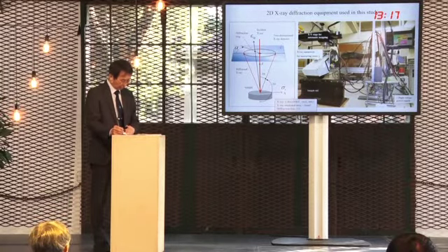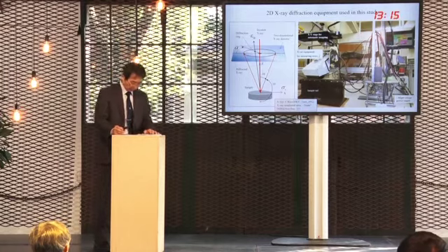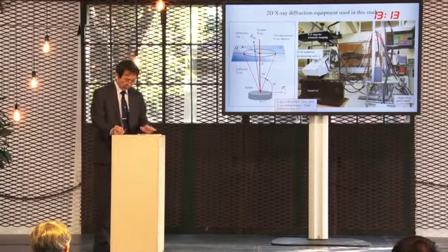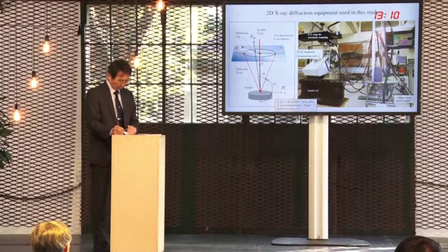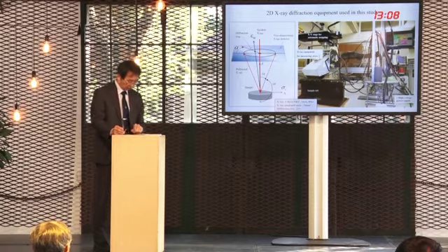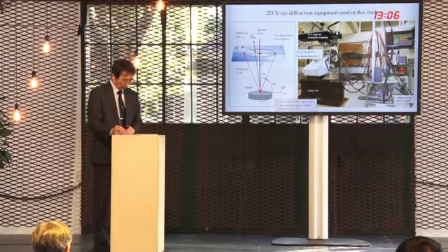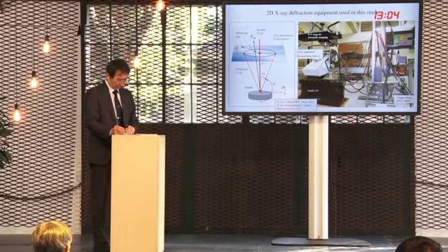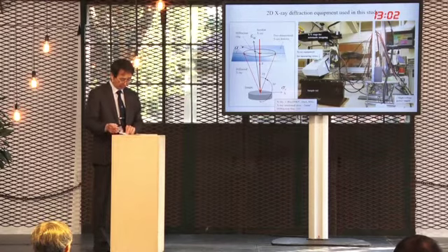The countermeasure to this RCF at the present is ultrasonic testing for detecting cracks and the grinding of rails for removing damaged layer before crack initiation. In my talk, I'd like to show that a newly developed two-dimensional X-ray diffraction method is effective for monitoring the early stage of the RCF.